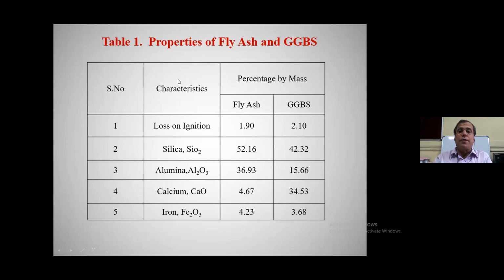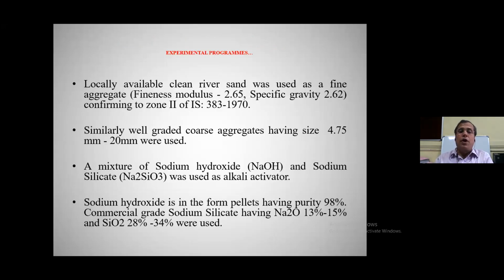You can see some of the properties of the fly ash and GGBS. Loss on ignition is 1.9 for fly ash and 2.1 for GGBS. Silica is 52 for fly ash, and this is 42 for GGBS. Alumina is 36.93 and 15.66. This is how our GGBS is helping us in getting a better heat of hydration, so that we can get the ambient-condition strength without going for temperature curing.